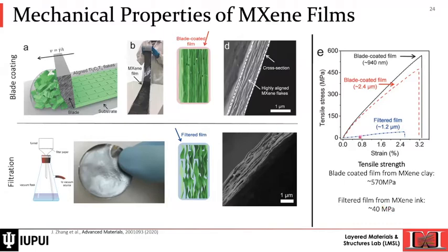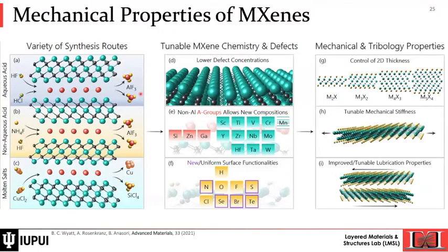So here's the filtered film, tensile strength, and here is the blade coated film. So you can see there's huge difference between the two. And there's no change of the nature of MXene. This is just based on the alignment of MXene. So to wrap up this section of my talk, MXene mechanical properties is tunable. And we have several knobs to play with to control the mechanical properties of MXene.